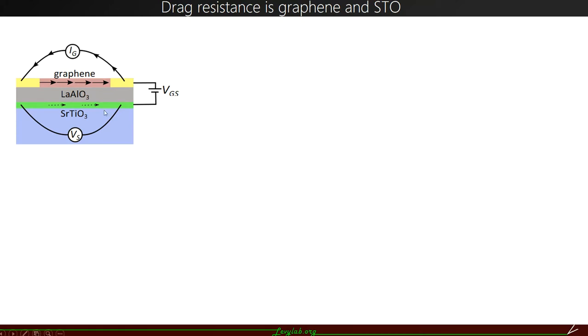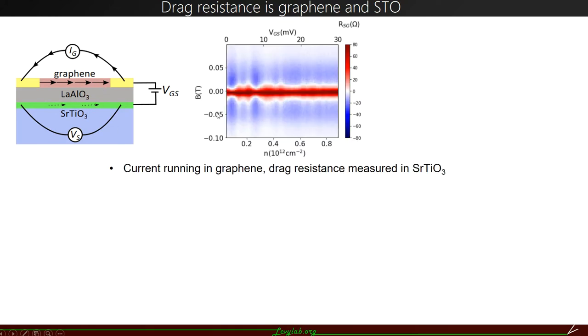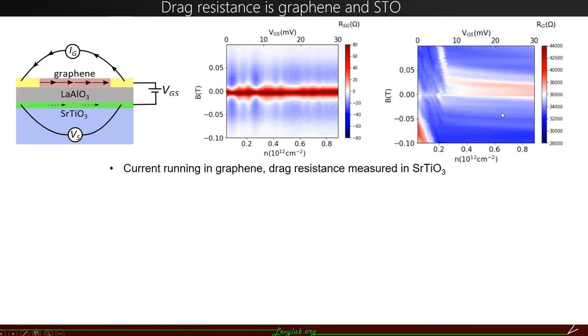First, we start running the current in graphene and measure the drag voltage in SrTiO. We plotted the drag voltage as a function of magnetic field and the carrier density in graphene. As we can see, the drag resistance is enhanced near the zero magnetic field region, and this is the corresponding voltage in graphene measured at the same time.